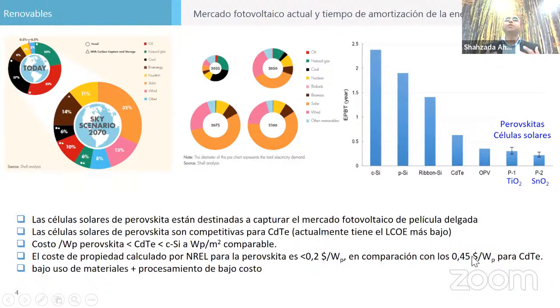Why did it happen? Because we use less material and we use very low processing cost equipment. Just to give you a flavor, silicon is 200 to 300 micron. Thin film technology is 3 micron. Perovskite solar cells with active material is 400 nanometers, an order of magnitude lower. And this order of magnitude lower will bring down the cost.